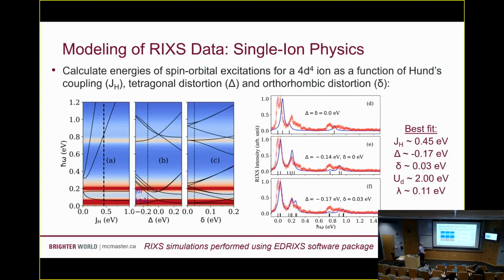Okay? So without going into too many details, I'll just say you can calculate theoretical RIXS spectra here, and you can use the position of what we called peak C before. So this was going from the ground state multiplet to the first Hund's multiplet. That lets you pick the energy scale for the Hund's coupling. You can then look at the position of some of these other features, and you can use that to set this tetragonal crystal electric field splitting.